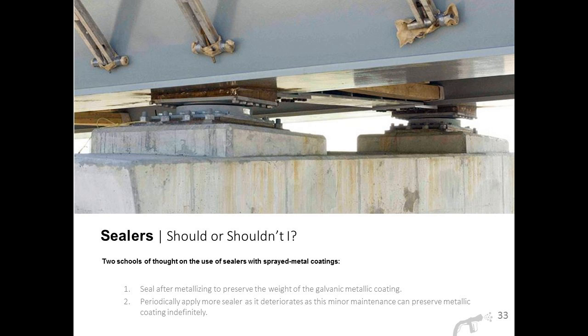The second school of thought really is more sealer. You can add more sealer on a 10-year basis or so, or a 15-year basis or so, to extend the life of the metallized surface below. And probably what we see more often in the field is a lot of states just choose not to seal at all. Through all the research and studies that we've seen, 30 years with an unsealed metallized coating is not far off at all. It's pretty well expected.